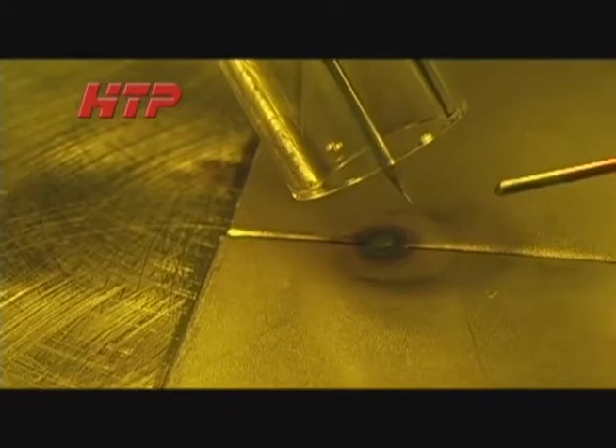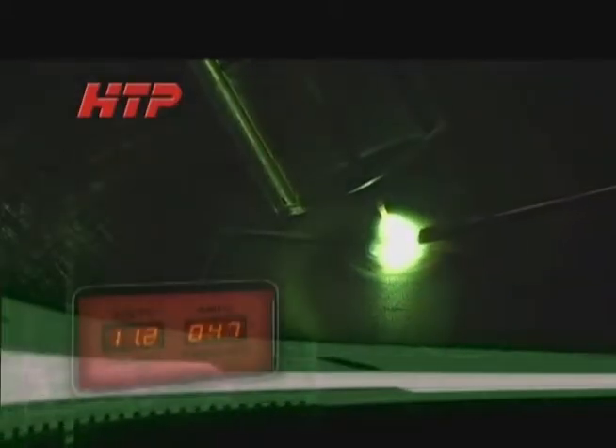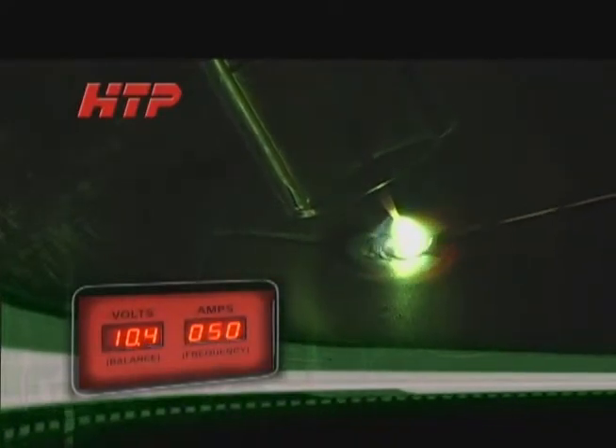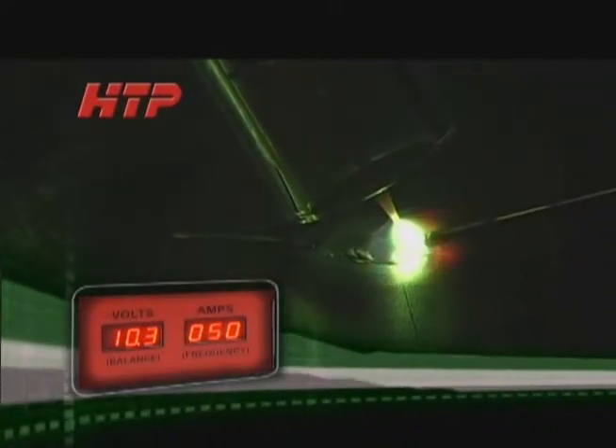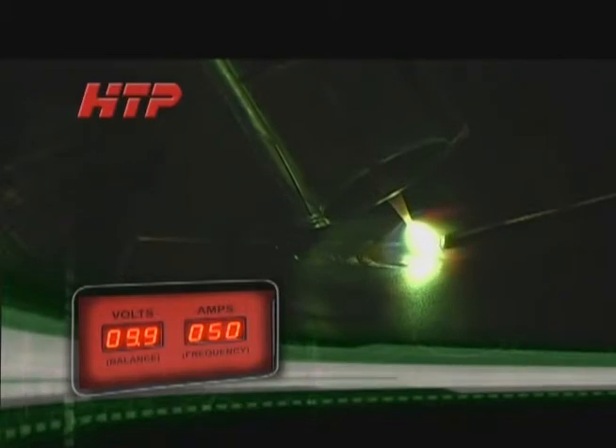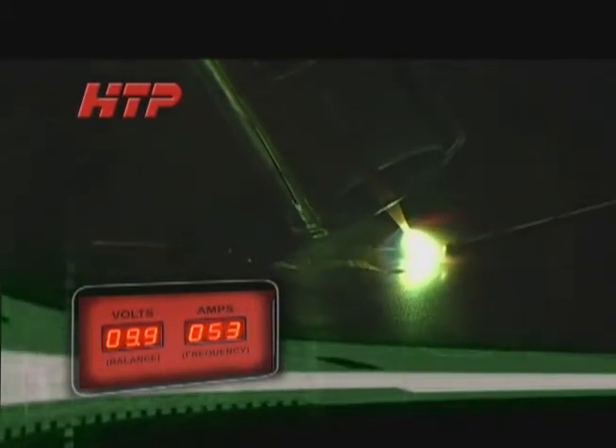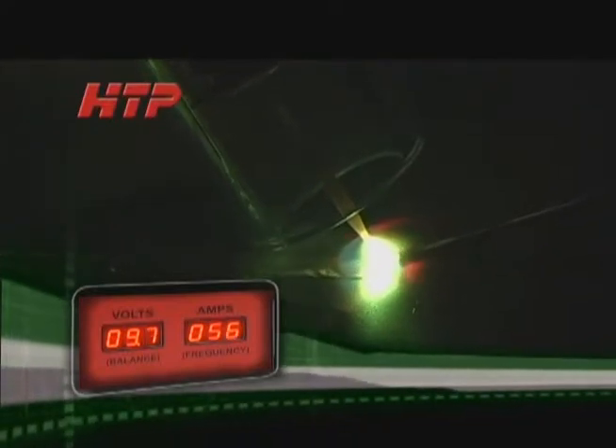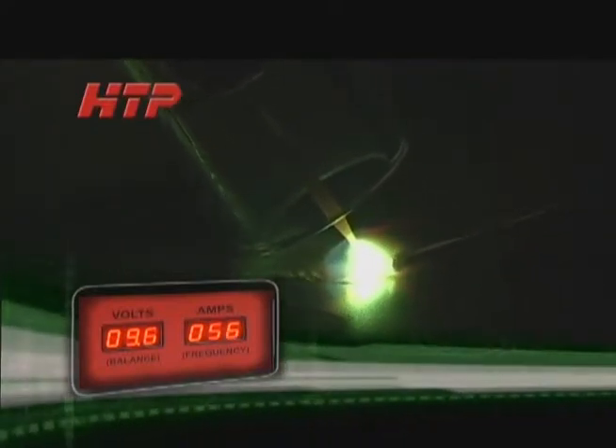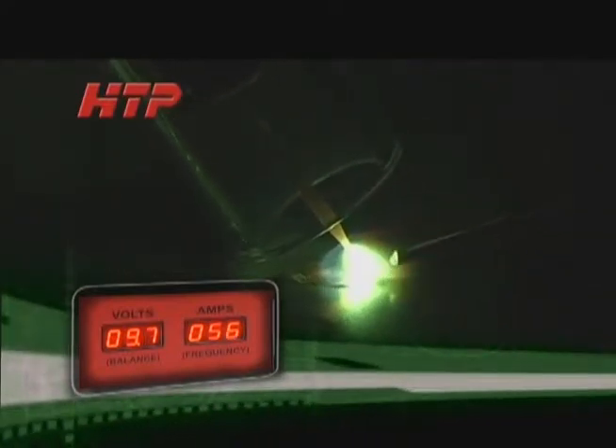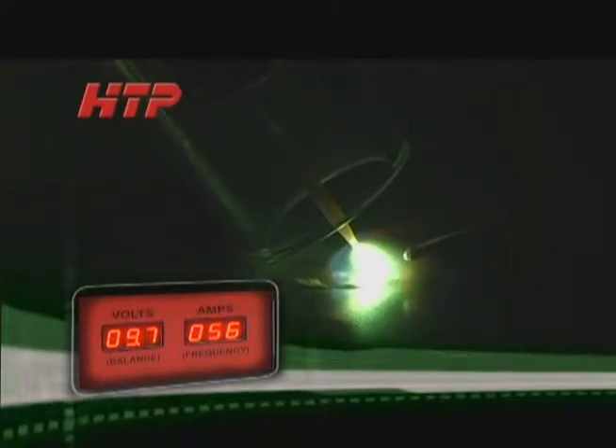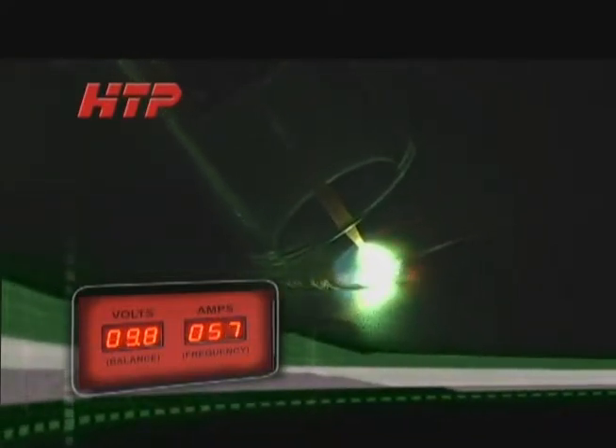Again, depress the pedal to get a molten puddle and dab the filler metal in. Keep the tungsten centered over the joint where the 2 panels meet and dab the filler into the molten puddle. Don't melt the filler with the flame of the torch. We are running about 50 to 55 amps.